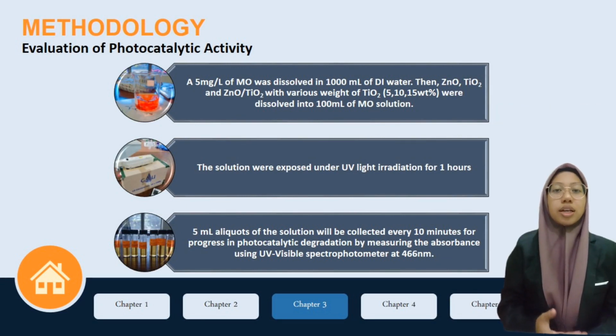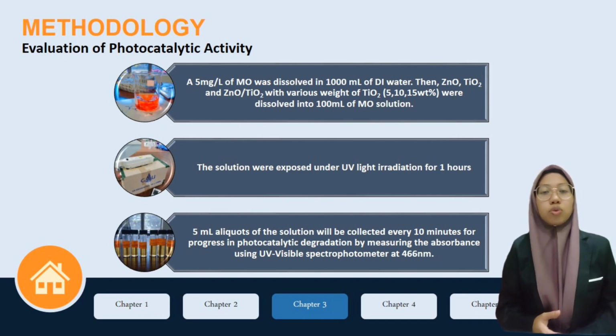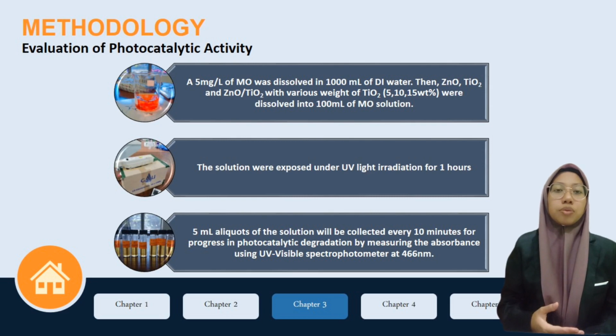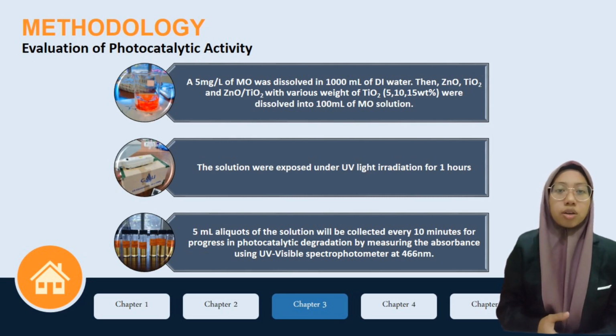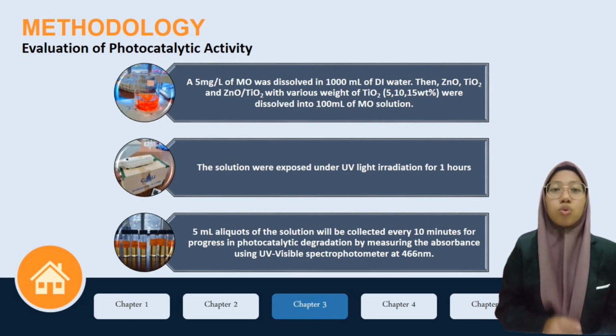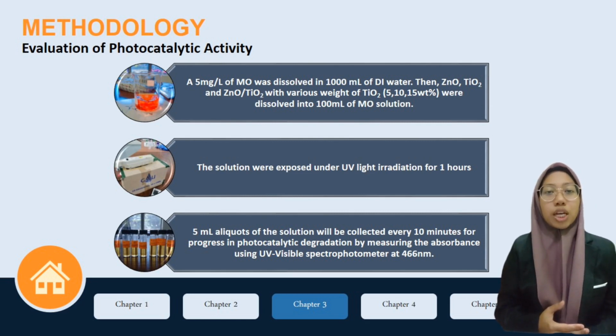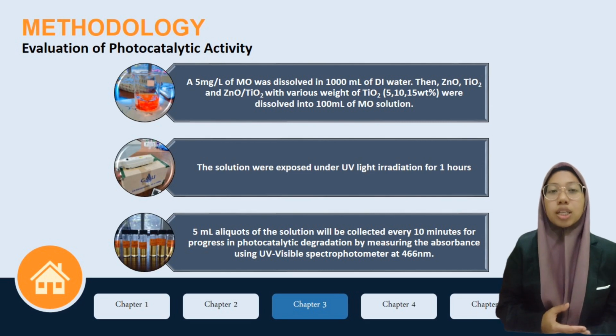Then the zinc oxide and titanium dioxide doped zinc oxide with various weights of titanium dioxide were dissolved into 100 ml of methyl orange solution. The solution was exposed under UV light irradiation for 1 hour. 5 ml aliquots of the solution were collected every 10 minutes for progress in photocatalytic degradation by measuring the